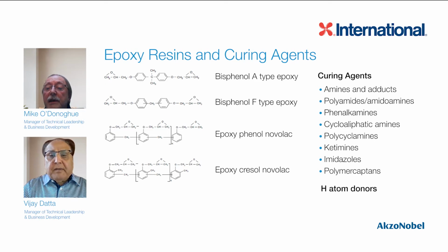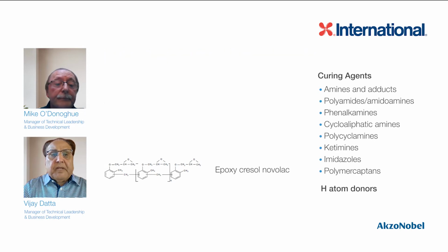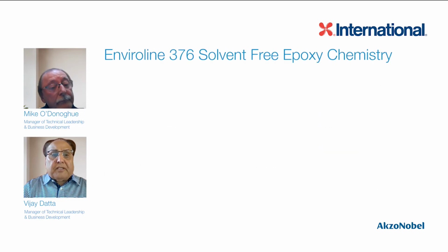Yes, as you can see, there's a variety of them, and each of them provides a hydrogen atom to react with the oxygen on the epoxide group. And primarily in the oil patch nowadays, we're using the Novolac epoxies, and we're cross-linking those with the polycyclamines that you can tell us about with the Enviroline 376. But there's a variety of curing agents, as you see, and they're all providing hydrogen atoms to react and co-react with the epoxy. Now, look at this diagram here.